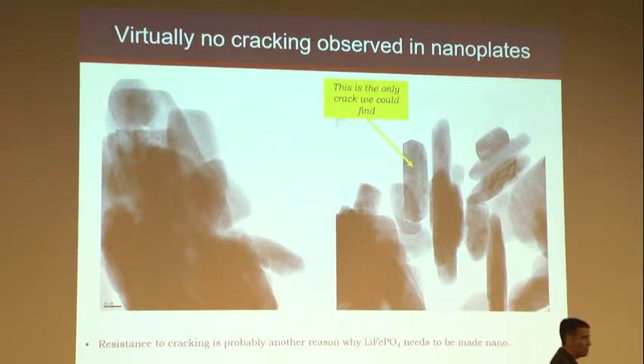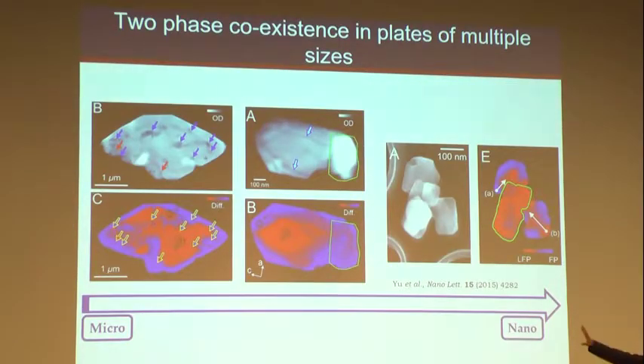And so what these all revealed is that even though the distribution of domains is not really that different, you still see that trend that delithiation is happening at the edges of the particles. The big difference between the three sizes was that the two bigger sizes fracture when they dilithiate, and the smaller sizes do not. And so that's something that had been formulated over time about battery materials, that if you make them small enough, they can bypass fracture. And that's one of the reasons why, if you ever read about lithium iron phosphate, you hear that you need to make it nanometric for it to operate. And so there are other reasons, but this is one of them.